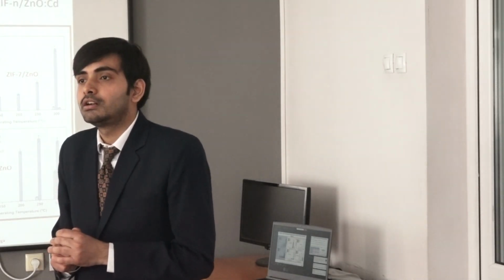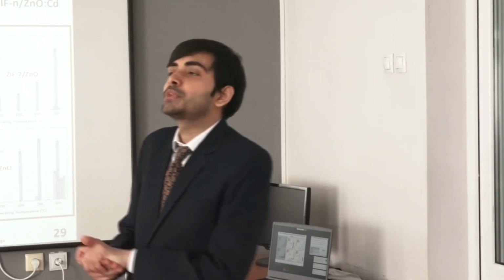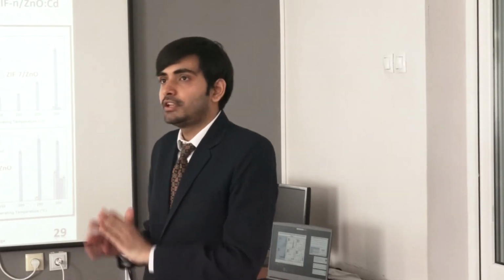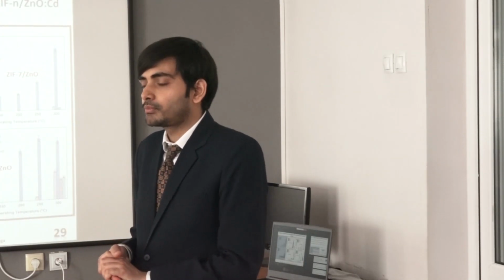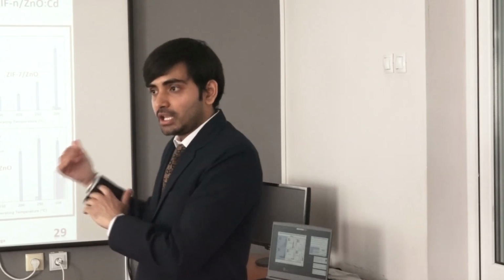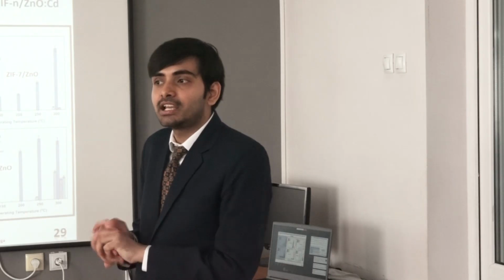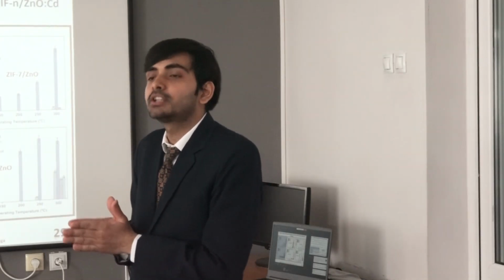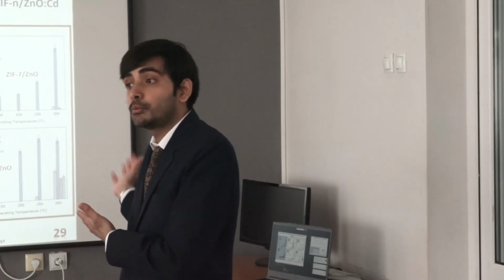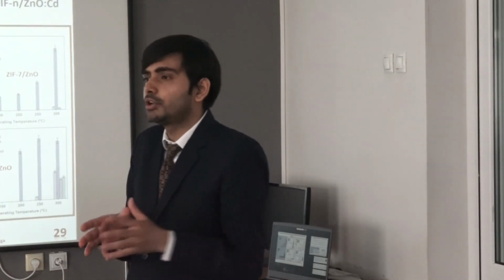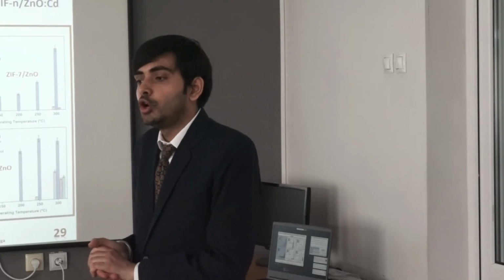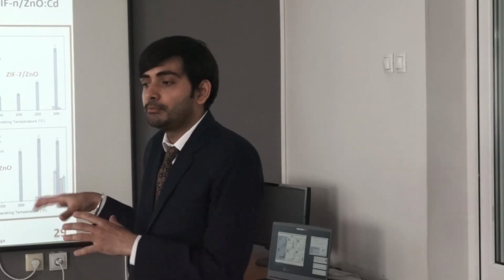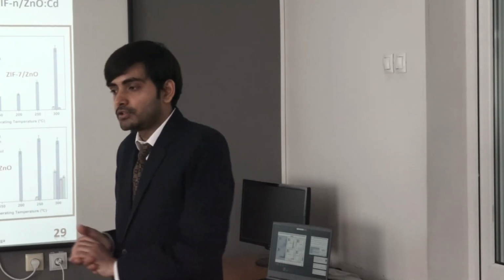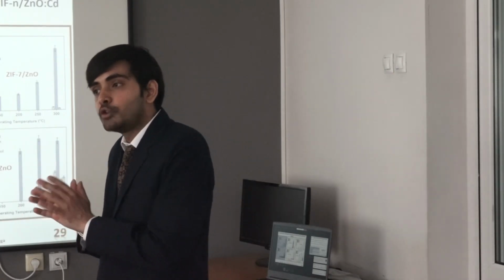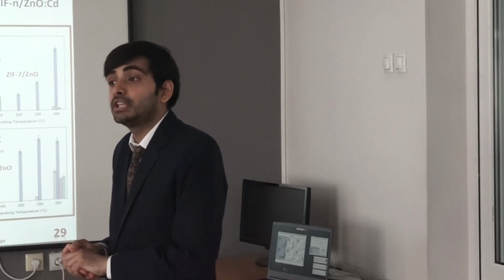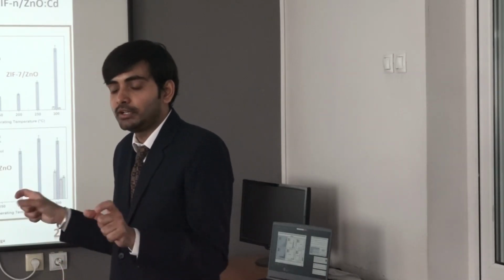In the developed hybrid structures there is no uniform layer. Yeah, so as I've already mentioned in my slides and detailed in the thesis as well, and as the Professor also pointed out, intrinsically there is a contribution from the Knudsen diffusion regime, but through defects or grain boundaries there might be a contribution from 2 other regimes including the molecular regime or transitional diffusion regime. So in this study I tried to be conservative, so that it is not 100% from the Knudsen diffusion regime, but there might be a contribution from defects or definitely from the other 2 regimes.